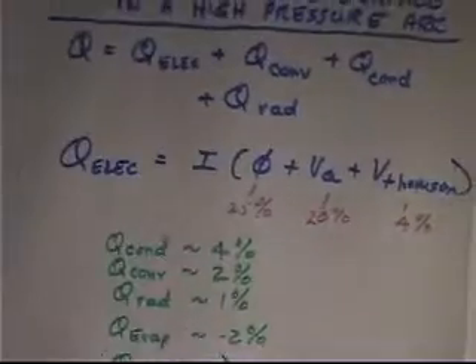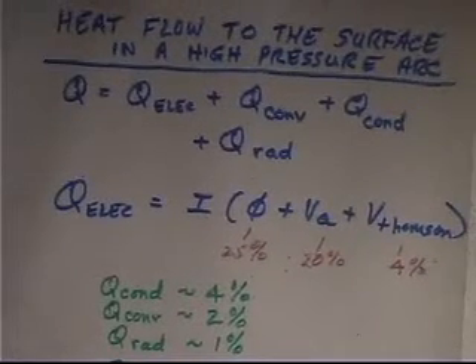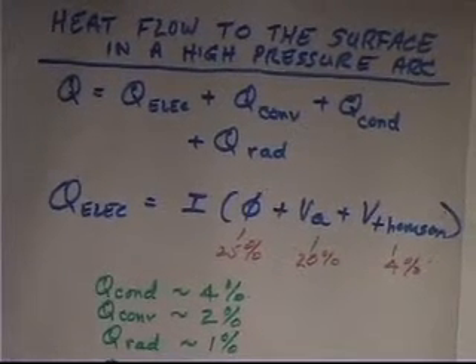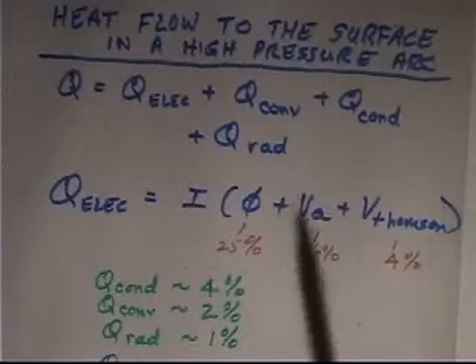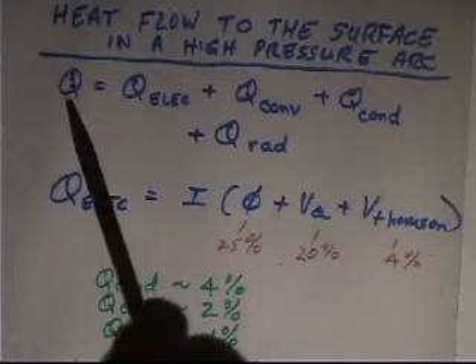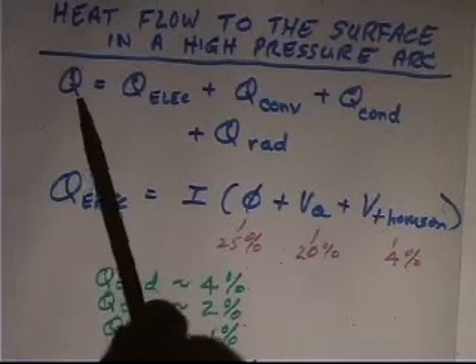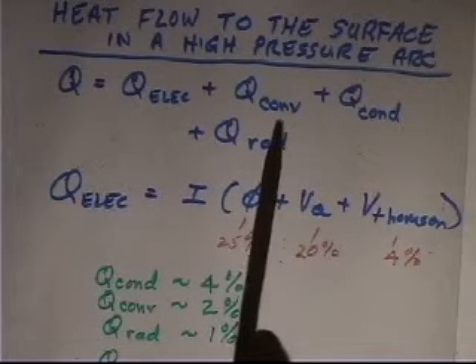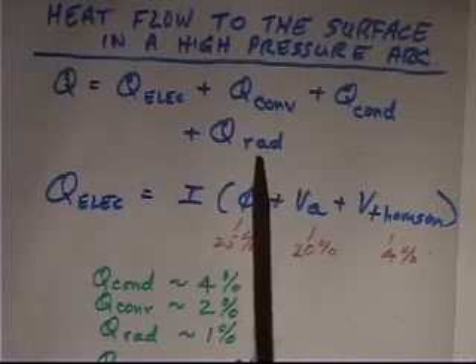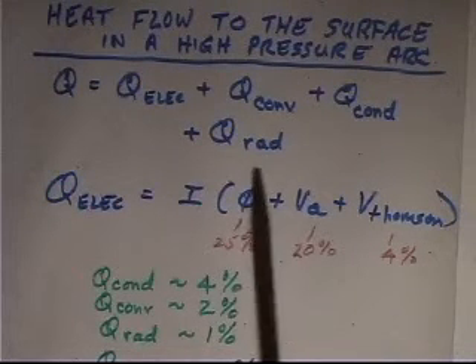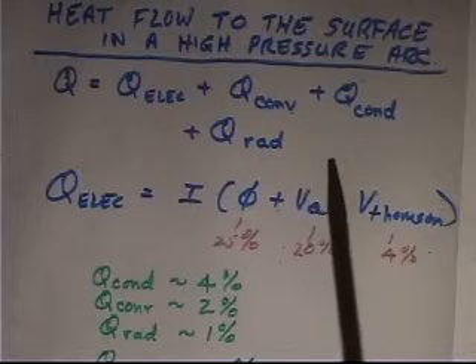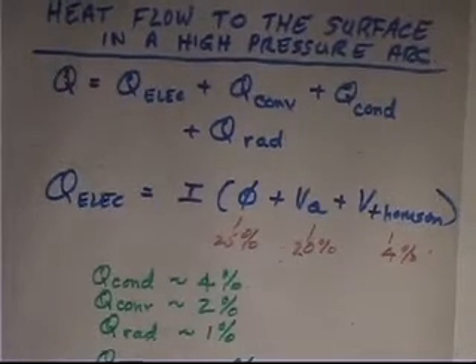Now, if we want to look at heat flow to the surface in a high pressure arc, you have a paper that some of this comes out of. I've modified the numbers a little bit. It's a paper by Metcalf and Quigley, and they pointed out that the heat to the surface, Q, the total heat, is equal to the heat from electron flow, convective heat from the hot gas, conductive heat through the hot gas, plus radiation heat from the gas to the workpiece. You can also subtract off the radiation from the workpiece out, which they do in their paper, and you can subtract off evaporative heat and other things.